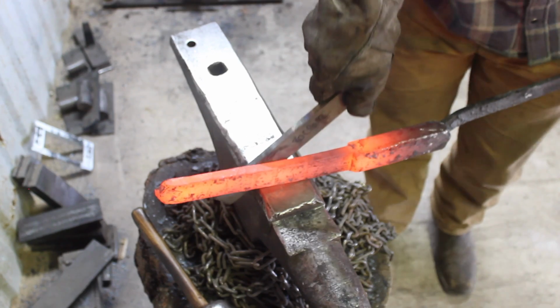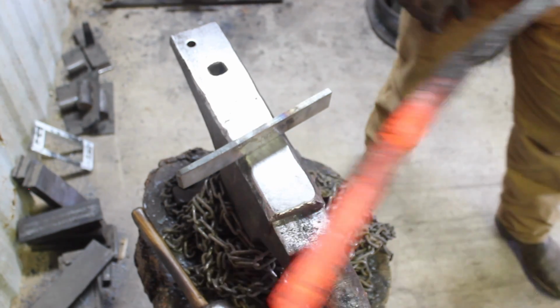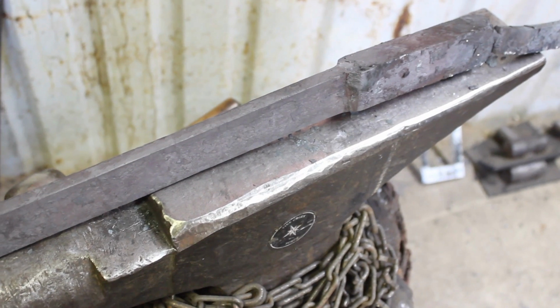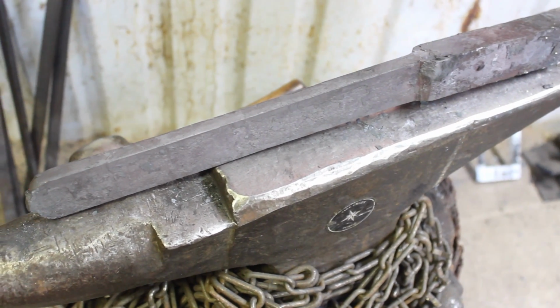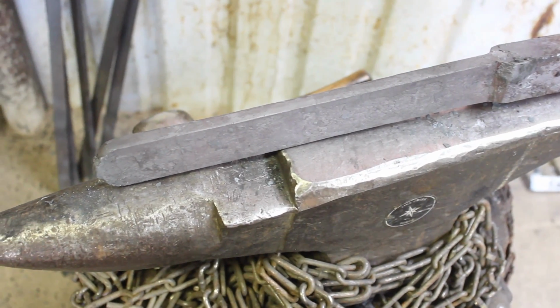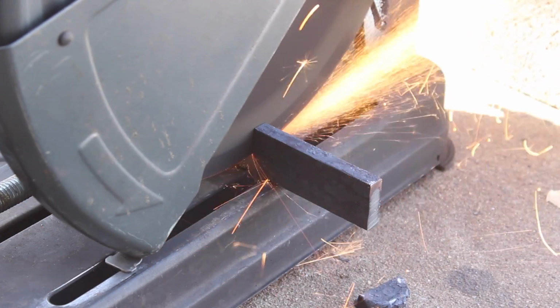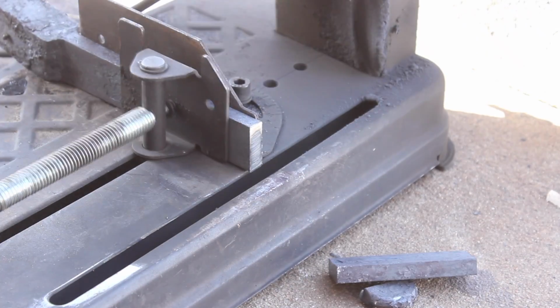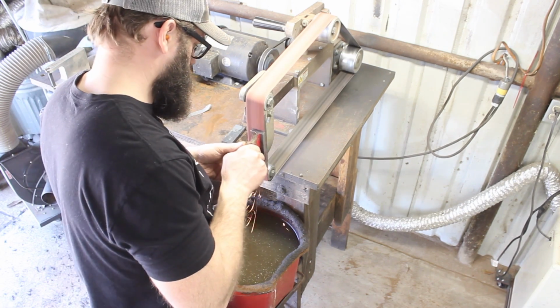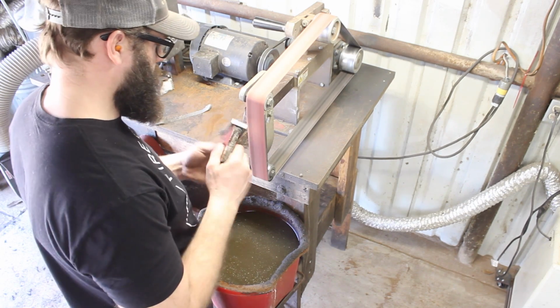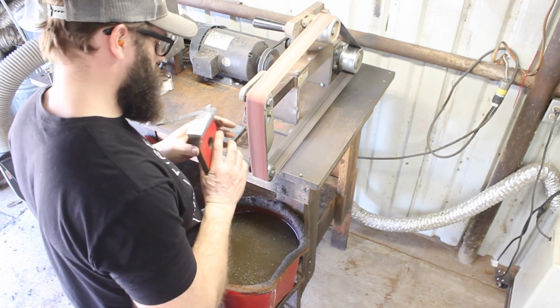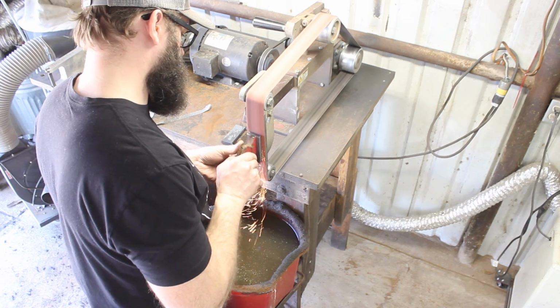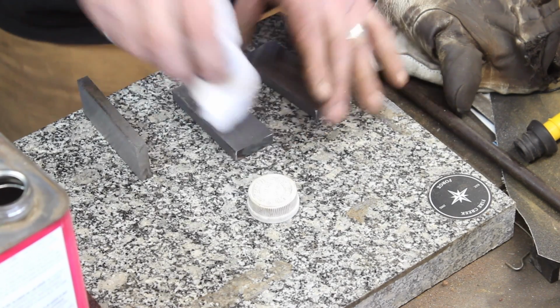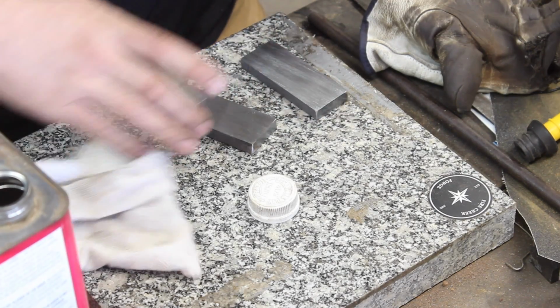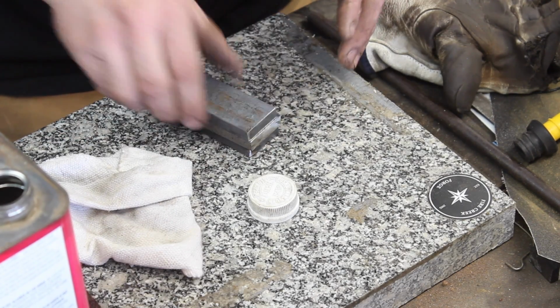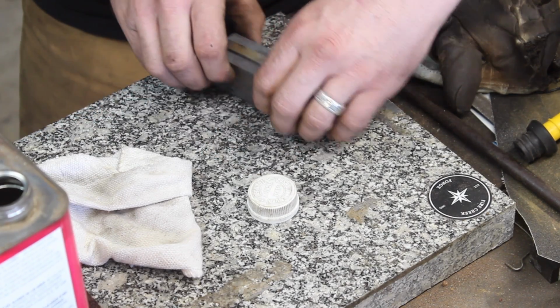But I want my Damascus cladding pieces to be a little thicker than that, because I still have to grind off the forge scale and get a clean surface to, again, forge weld those pieces together. And then on the final finish of the knife, I'm going to have to grind off the outer layer to finish the blade. So the end result should be pretty equal amounts of steel across those three different pieces in our Sanmai construction. So again, being meticulous, and the steel's a little hot here to handle, but making sure everything is clean and ready to go.